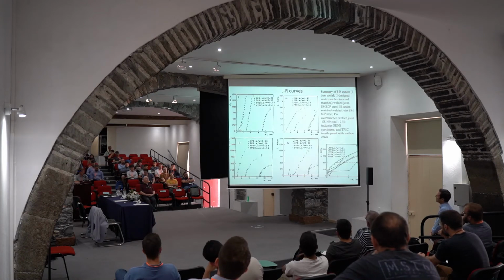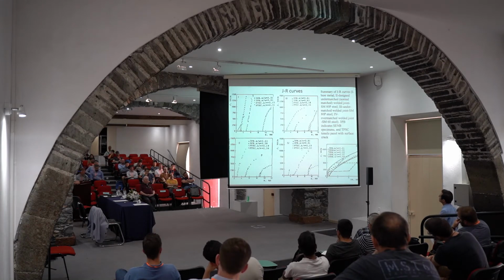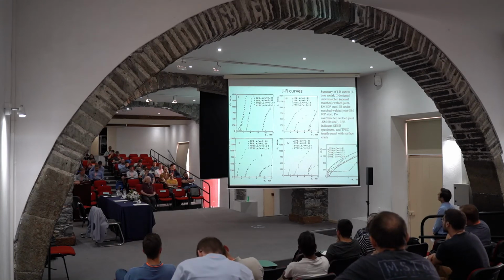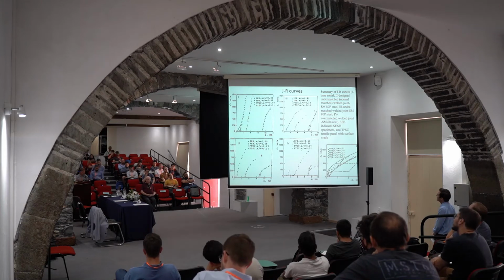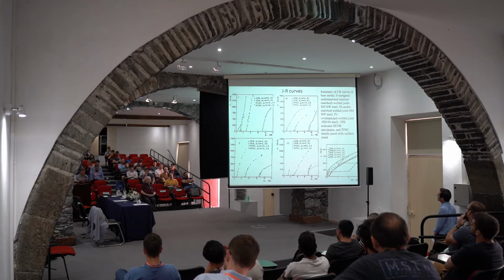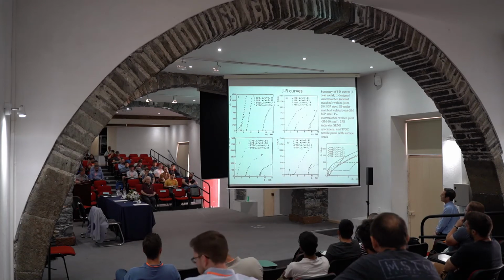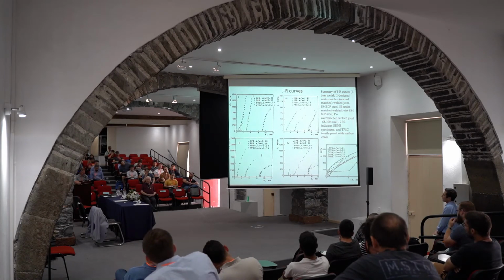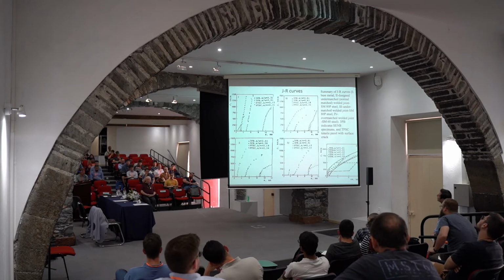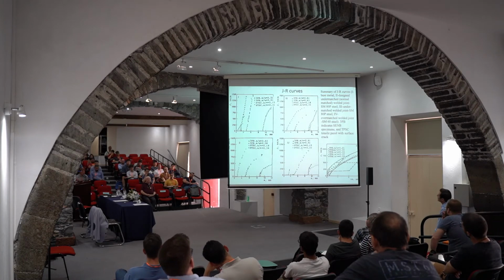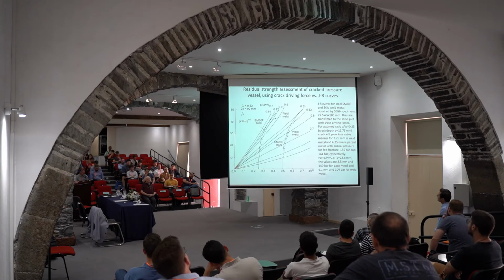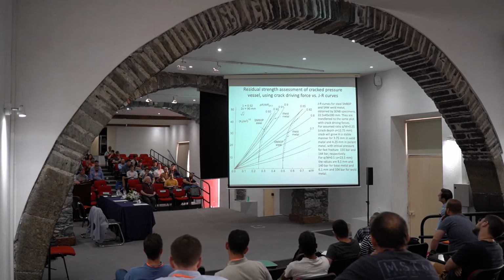And we got different JR curves. You can see them here. Of course, those obtained by tensile panels were closer to reality, and those obtained by 3-point bending were more conservative, which is not a bad thing to have, especially since our approach was not a very conservative one, as I explained at the beginning. So this is the result.